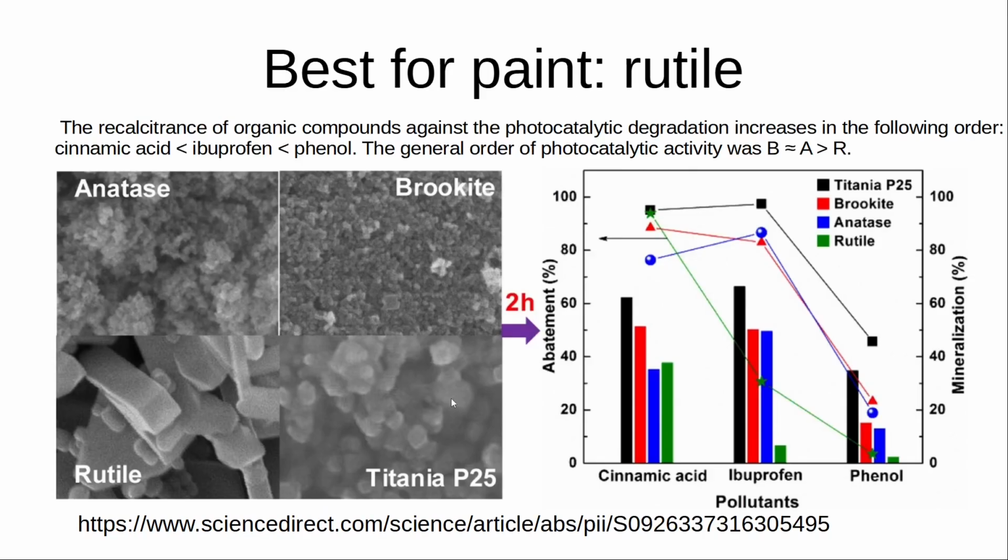Furthermore, if you look at the crystals over here, normally a smaller crystal will lead to a higher surface area, causing also faster activity. So there's two reasons in this case why the rutile was less active. You can see this is a very big crystal, so the surface area would be less, so the rutile for that reason will also be less active. So there's two parameters modifying the activity of the particular titania pigment.